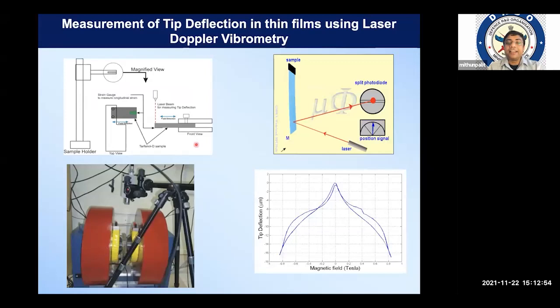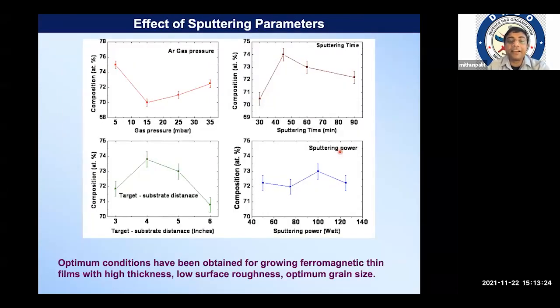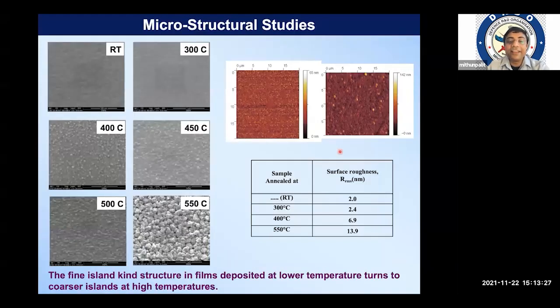And this is a special optical measurement technique for the magnetostriction in the film. You can see there is an optical camera, and the film is placed with a proper fixture between two magnetic pole pieces. And then you can see this schematic shows how we measure the deflection, and thus using a formula, the increase in the length of this thin film, or the deflection in the thin film, using these optical devices. And we have optimized a lot of sputtering parameters, and we have also explored depositing thin film at different substrate temperatures, starting from room temperature to 550 degrees C.